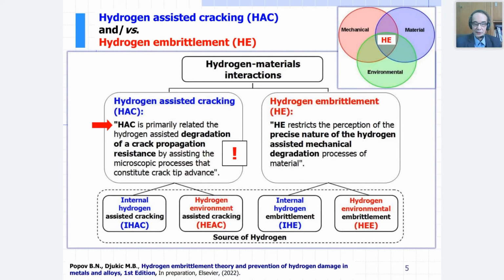When we talk about hydrogen-material interaction, just to make the distinction, hydrogen-assisted cracking is primarily related to the degradation of crack propagation resistance, which leads to the failure of the components. On the other hand, from the scientific point of view, hydrogen embrittlement relates to the perception of the precise nature of hydrogen-assisted mechanical degradation. And you have in the upper right part the 3 most important factors for hydrogen embrittlement, which are mechanical, material factors, and environmental factors.